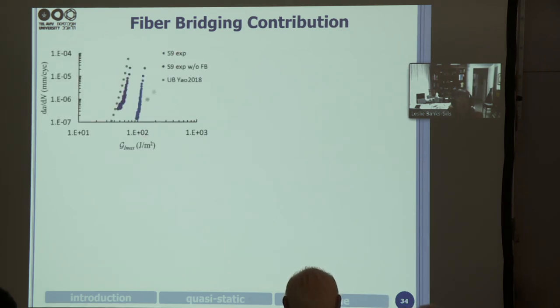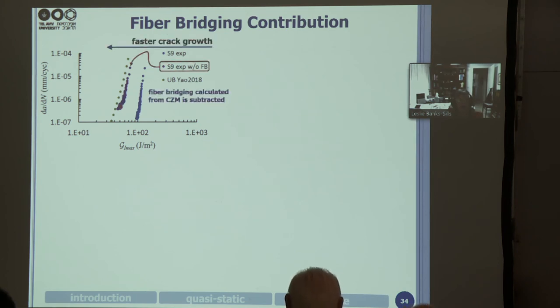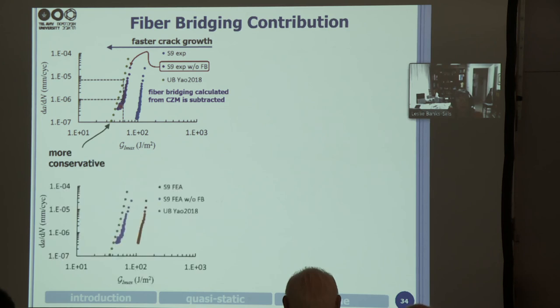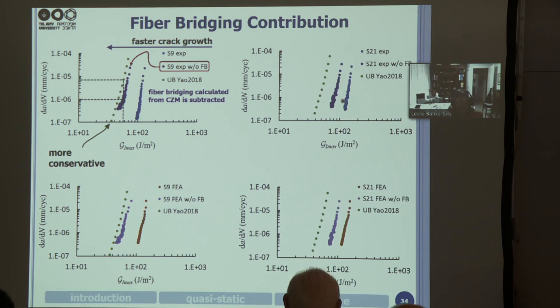And here you can see for specimen S9, the initial curve with the fiber bridging, and the curve of Yao in green and our curve in purple. Just go down to the next one, and this is the finite element results without fiber bridging and the Yao curve. And this is for the other specimen. This curve is less conservative than the Yao curve. So that's it. That's what we wanted to do. We wanted to have a method for eliminating fiber bridging. We can use their method or we can use our method. So we now have 2 methods for eliminating fiber bridging from our fatigue propagation.